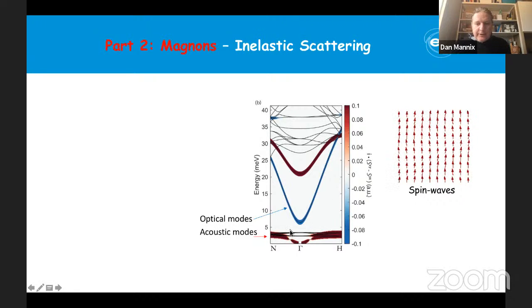The magnons, what we measure here in Q-space: you measure these dispersions of magnons with inelastic scattering. In these ferromagnetic materials, you can have different modes: an optical mode and an acoustic mode at lower energies. RIXS has an energy resolution of around 20 to 25 meV, so it's very difficult to study these low energy excitations, but you can study the higher energy ones. What we've been studying these with is neutron scattering.